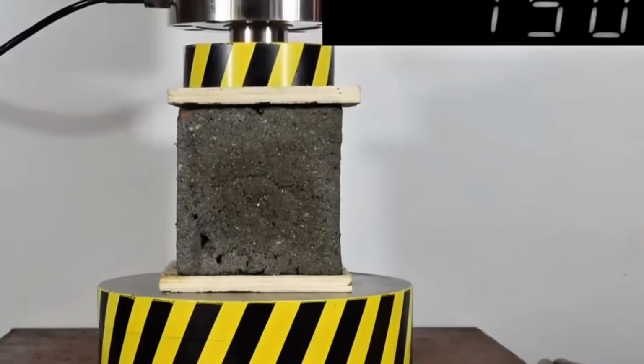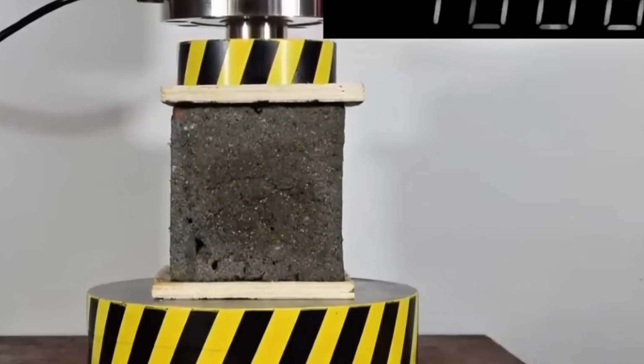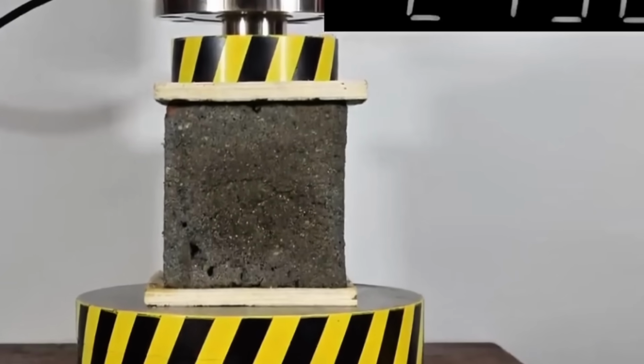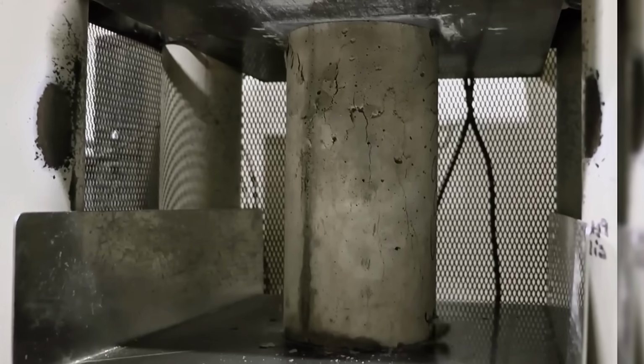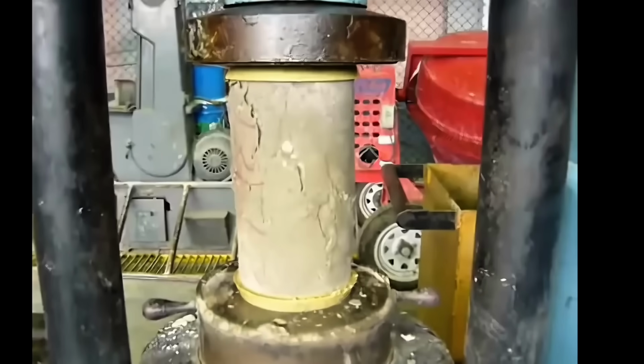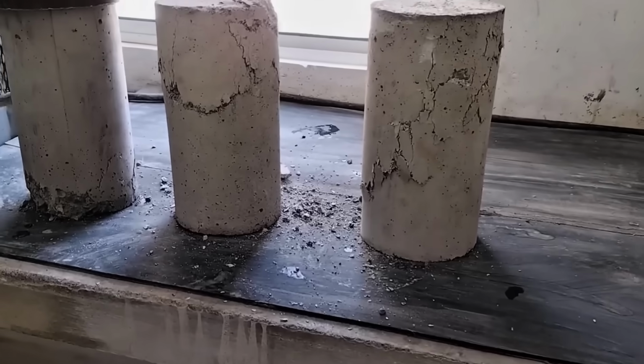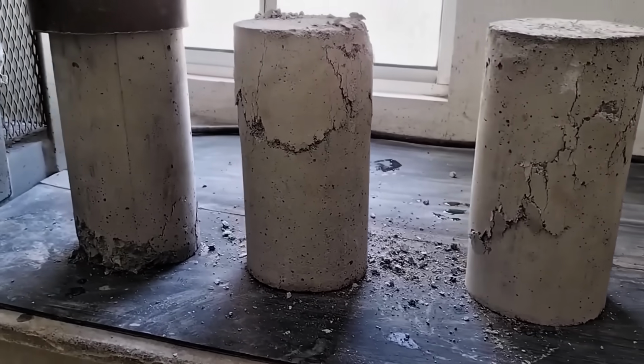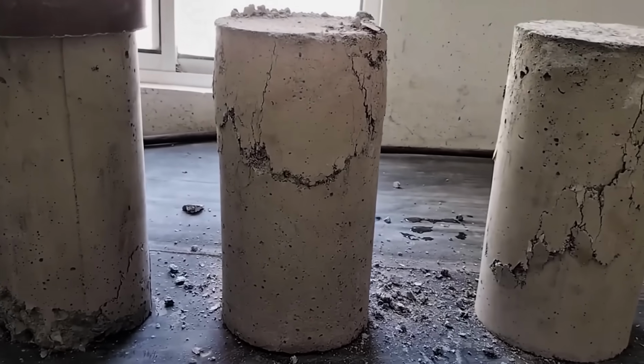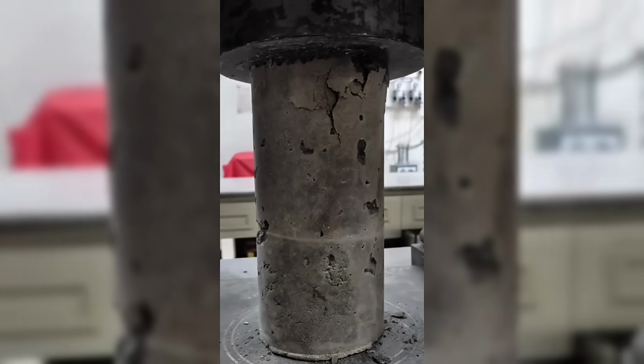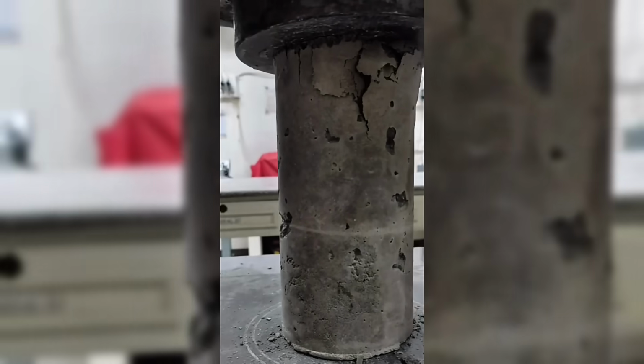Then, the cylinder is placed under a hydraulic press that gradually increases the load. You can see the pressure rise until the first cracks appear. Depending on the mix, the sample either shears along a single line or shatters. Experts analyze the failure pattern and compare it against standards to ensure the concrete on site meets the structural requirements.